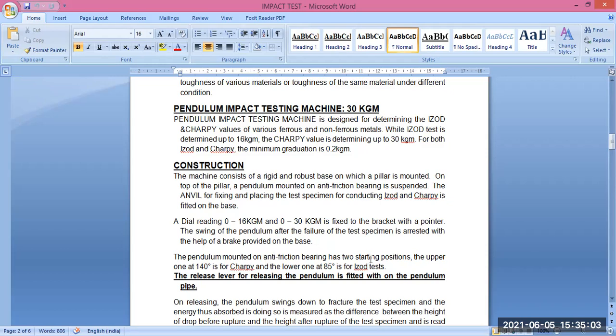The pendulum has two starting positions. The upper one, 140 degrees, is for Charpy, and the lower one is 85 degrees for the Izod test. The angle of release for Charpy is much higher than that of Izod, so it is creating a much higher breaking load from the machine on the workpiece itself.